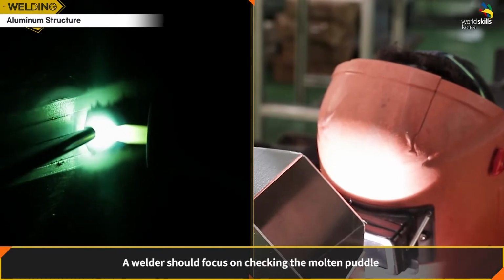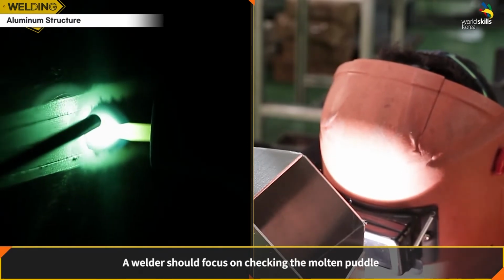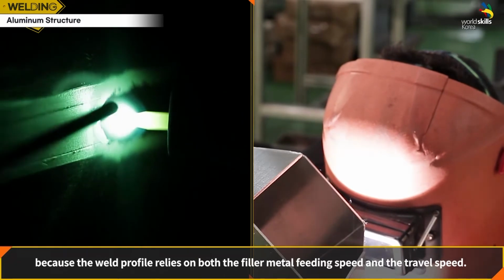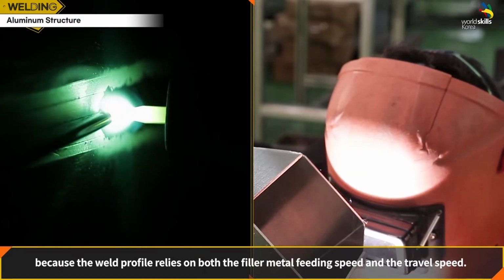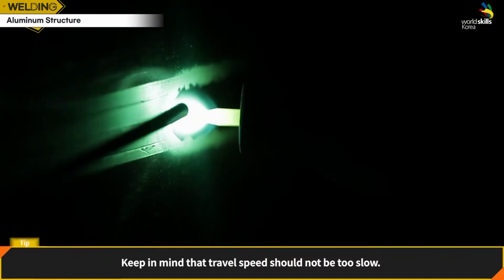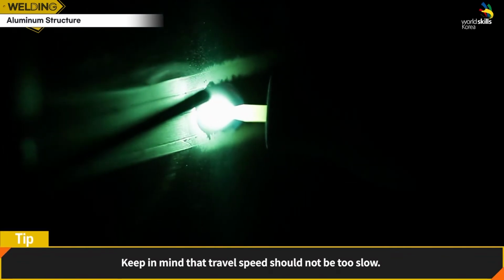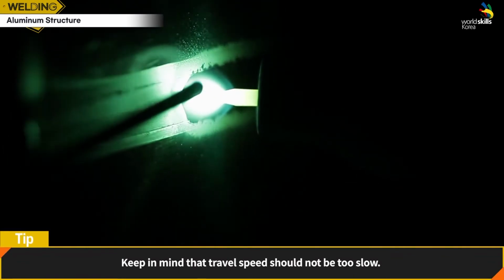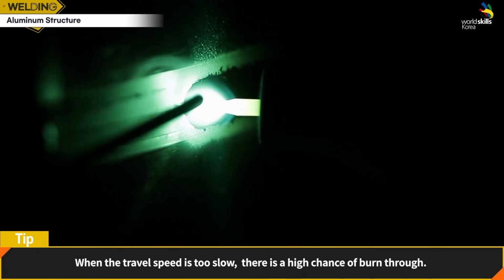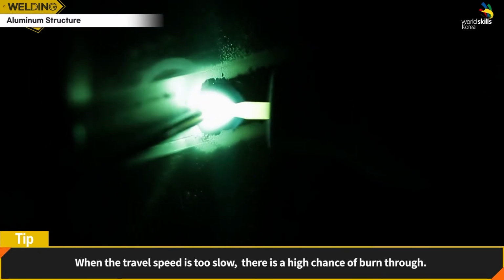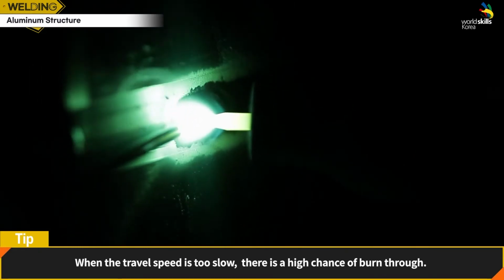A welder should focus on checking the molten puddle because the weld profile relies on both the filler metal feeding speed and the travel speed. Keep in mind that travel speed should not be too slow. When the travel speed is too slow, there is a high chance of burn-through.